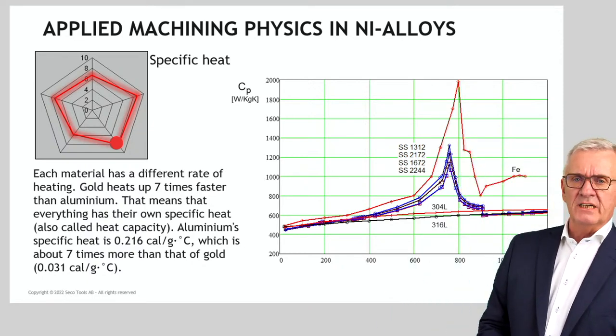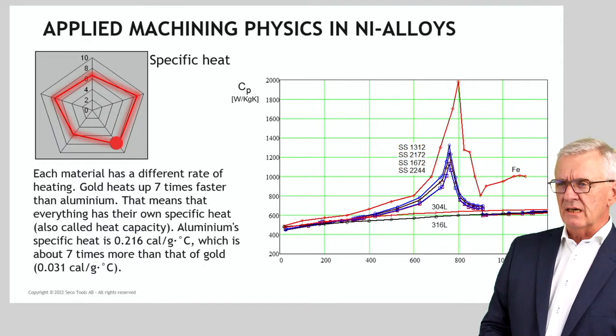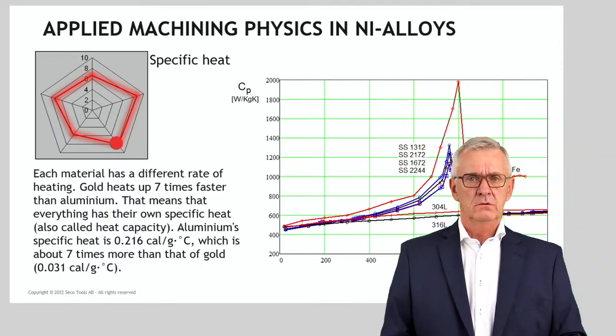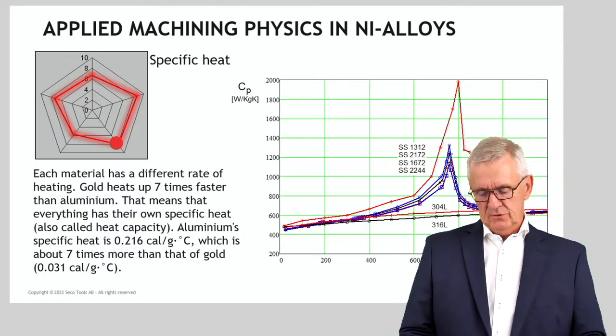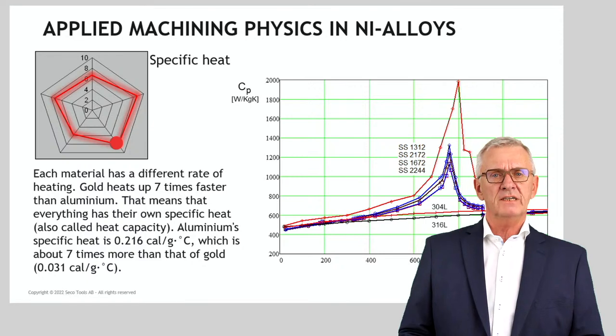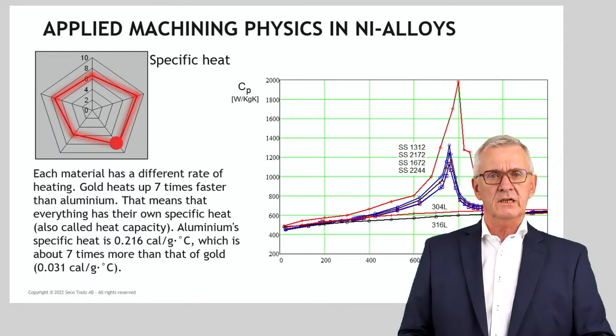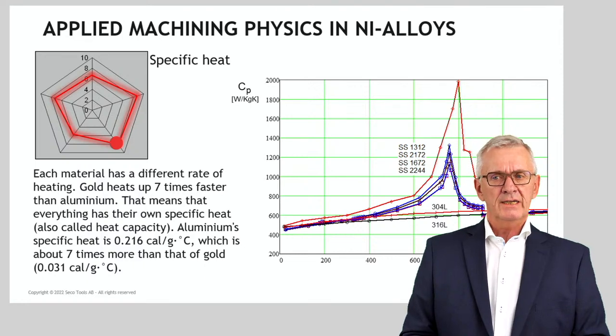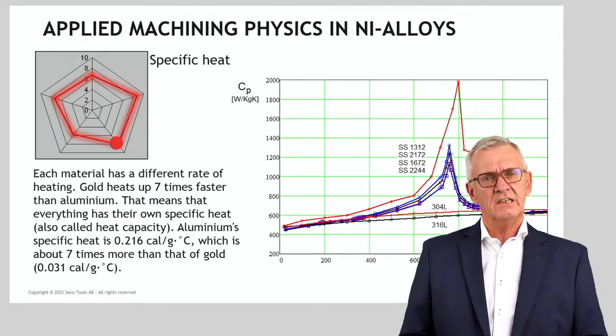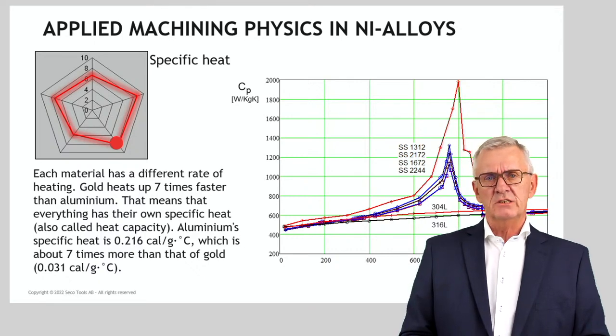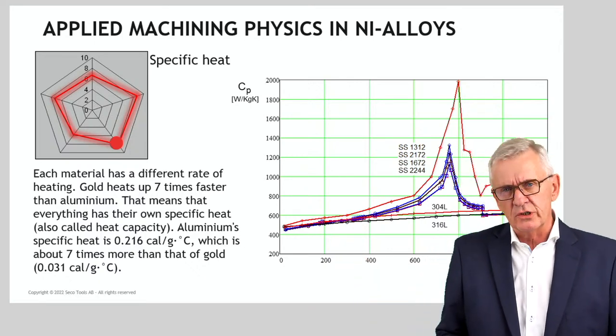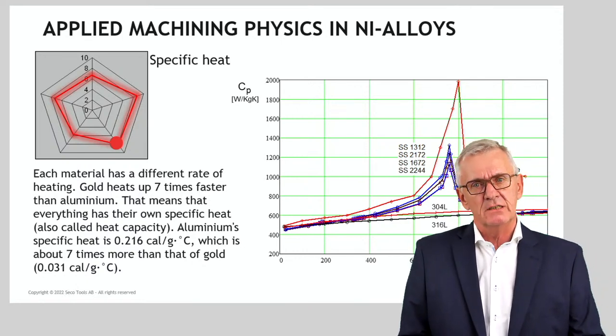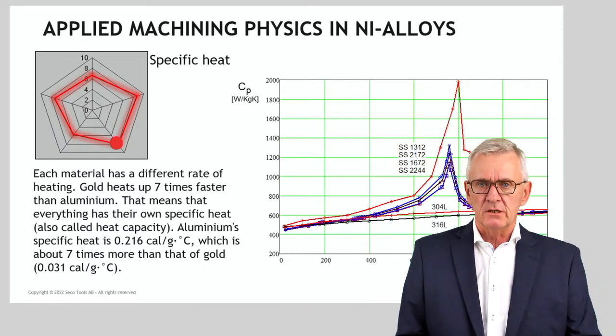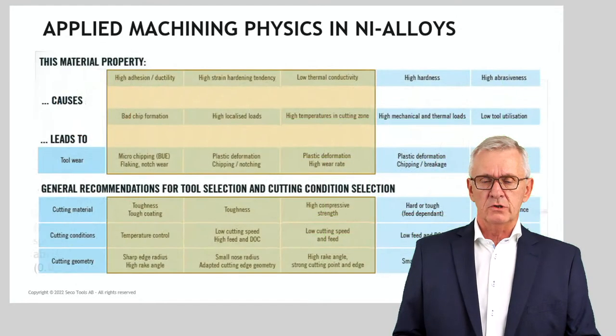But in nickel-based alloys, in stainless steels, the materials there, I hope it's visible, the ones in the bottom are most spectacular, 304L and 316L, austenitic stainless steels, they don't have that thermal wall. So even if you reach 800 degrees Celsius, a very small increase in cutting speed will continue to increase your temperature in the cutting zone. And that's why cutting speeds are so critical in this type of materials. Selecting cutting speeds in steel is not, I should not say not important, but less critical. But in superalloys, nickel-based alloys, your cutting conditions are very important.